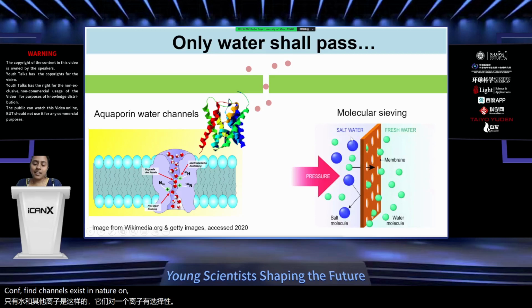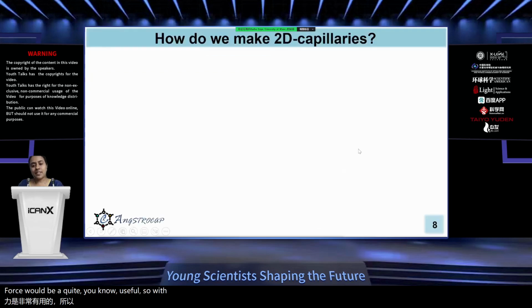On the other hand, it is quite interesting to have such channels for sieving purposes. For instance, if you are able to separate out salt from water, this kind of pores would be quite useful. So with that interest, we started making these kind of 2D channels, which can be of the dimensions of the molecules themselves. So I introduced the concept of two-dimensional voids, but how do we make them in practice?